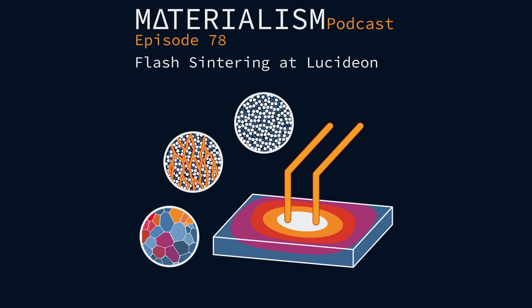Yeah, indeed. With the contactless, there are geometrical limitations as well. It has to be a thin sample so as to sinter without inducing too much mechanical strain as you're getting that shrinkage. We've sintered and looked at rastering samples anywhere from tens of microns to a few hundred microns thick.